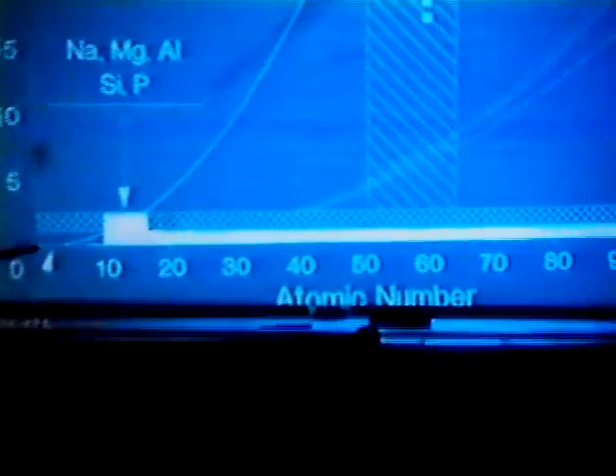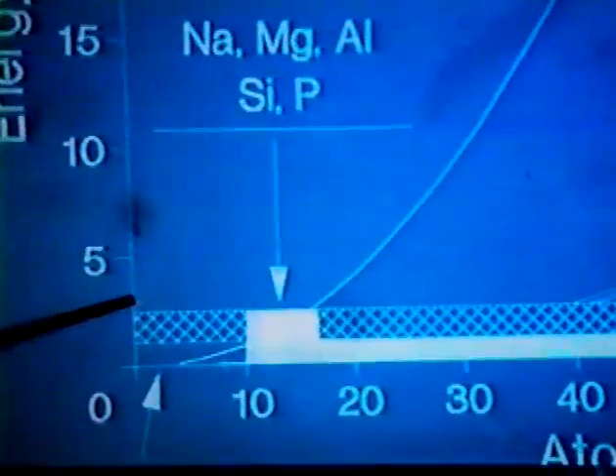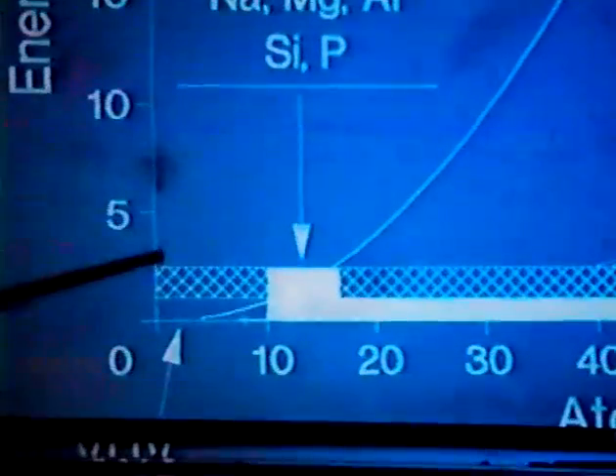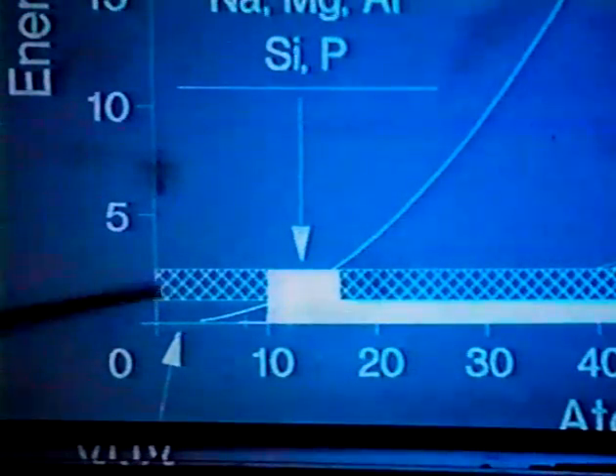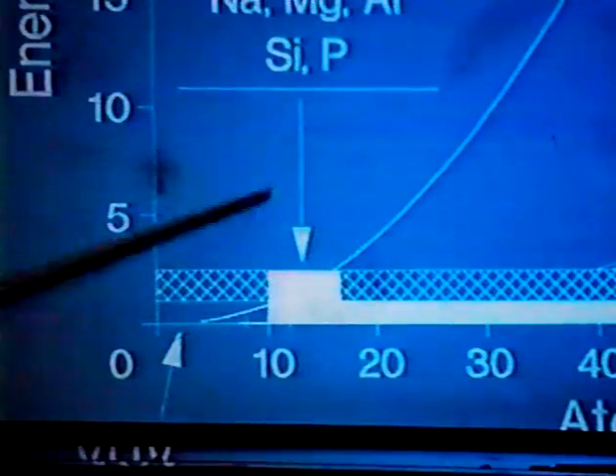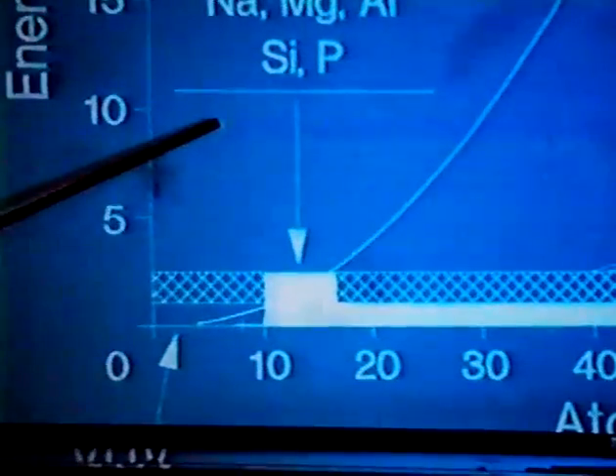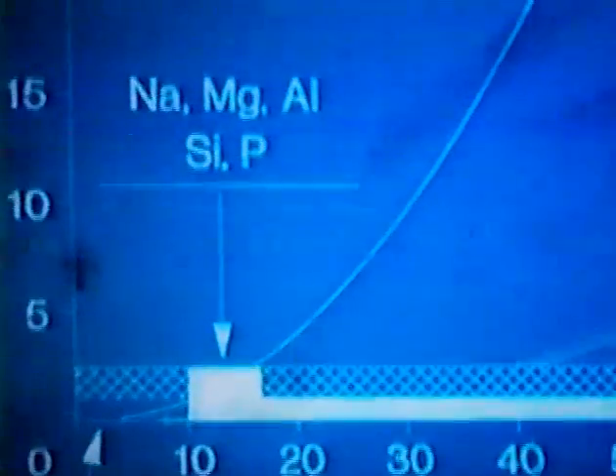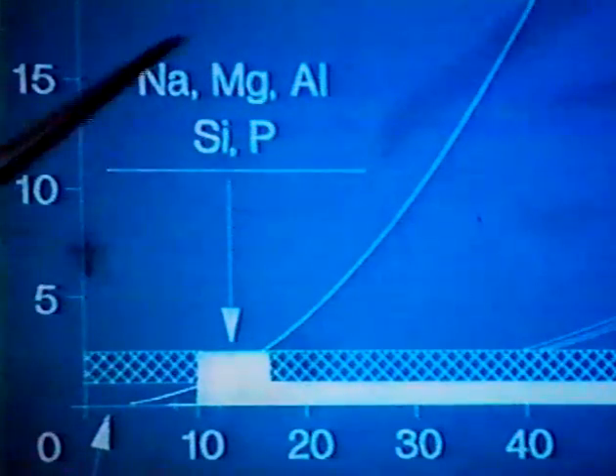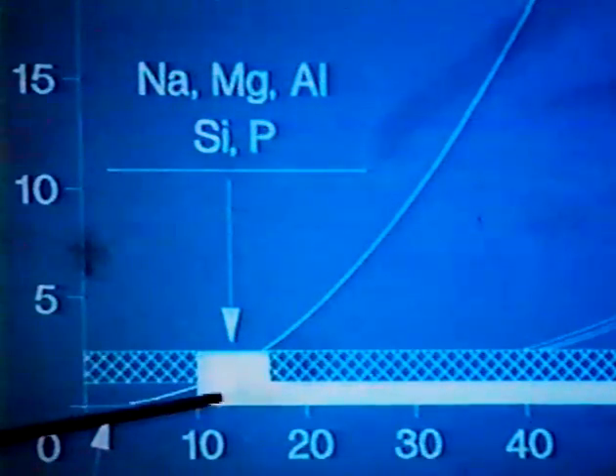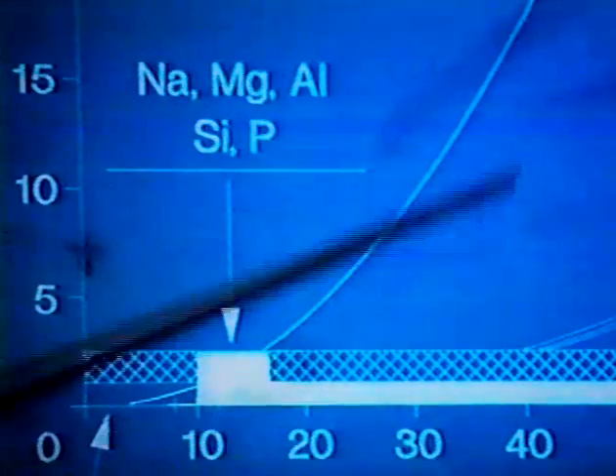Now down here at low energy, there's a gap. The VUV sources and soft X-ray sources furnish photons up to about 1,000 electron volts, and the X-ray sources furnish photons down to about 3,000 electron volts. And in between, there's a region that isn't really covered by any source. Unfortunately, that's where sodium, magnesium, aluminum, silicon, and phosphorus absorb. So those important elements are kind of hard to do these kinds of measurements with.